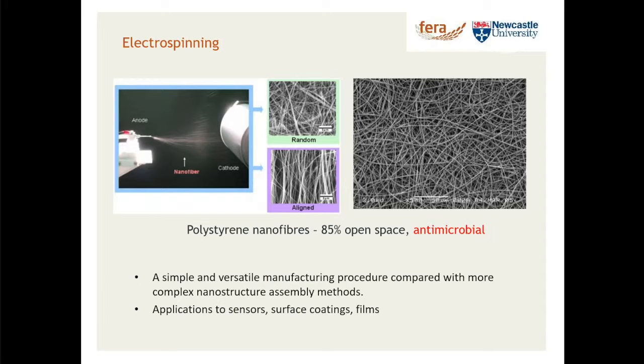And quite a lot of materials can actually be spun into a fibrous network. This is actually used for creating things like filters. But again, it can be used for coating surfaces, for coating films, or being the film itself, and various other possibilities. And depending on how it's collected, you can either have random arrangements or even more organized arrangements. So some of the early work was done with polystyrene, which was then found to become antimicrobial, and the fibers themselves start to exhibit this antimicrobial effect, which appears to be related to their size. When we have these fine fibers, there's a high surface charge density, which is believed to be the reason behind the destruction or damage to microbial cell walls, for example. So lots of potential applications for these materials, but we don't want to be using polystyrene perhaps.